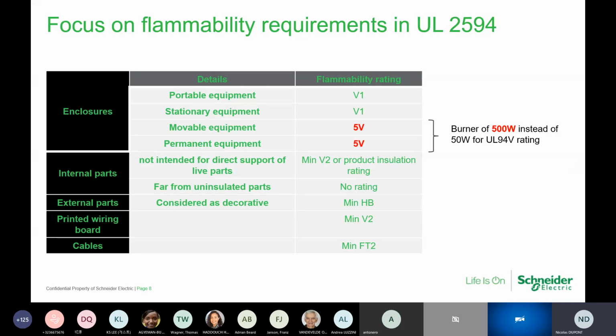And moreover, the flame is applied 5 times instead of 2, and the combustion should stop before 60 seconds without any flaming droplets. So this rating can be achieved only with flame retarded polymer, and consequently the enclosure which has been developed for IEC compliance cannot be directly used for the US market.